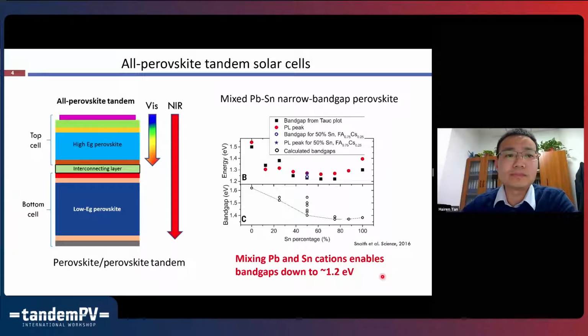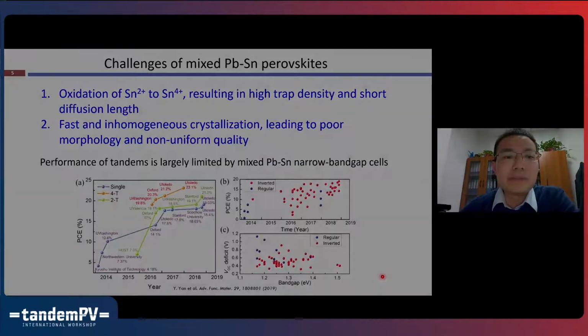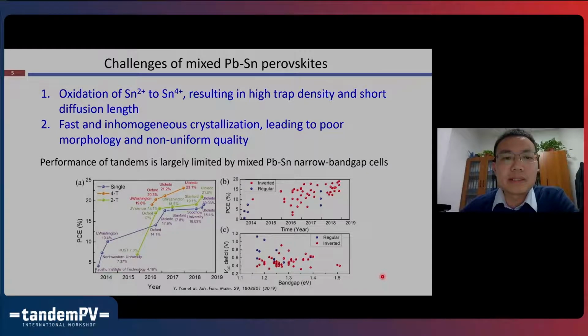But still, when we first wanted to make the mixed lead-tin based narrow band gap perovskite solar cells, we encountered two challenges. The first challenge is the ready oxidation of the tin 2+ ions to 4+ ions, not only in the precursor solutions but also in the perovskite material itself. This usually results in very high trap density and short diffusion length in the material. Also, due to the inclusion of tin in the B-site cations, we often see the crystallization is very fast, and the film is inhomogeneous. This will often lead to poor morphology and non-uniform quality in the resulting perovskite film.